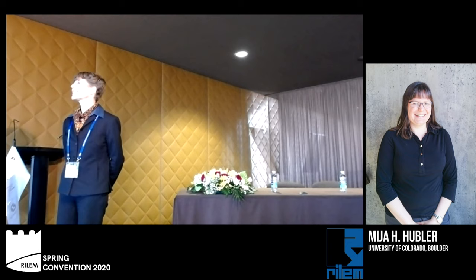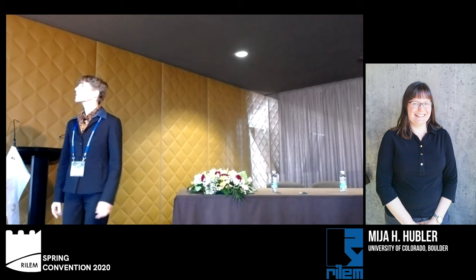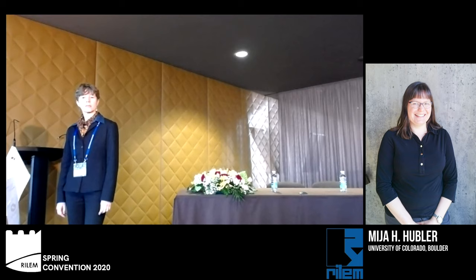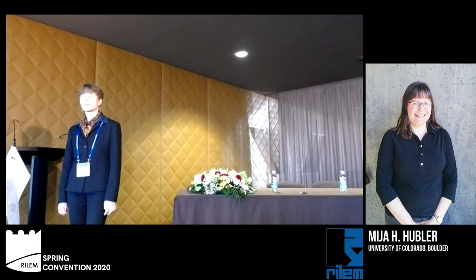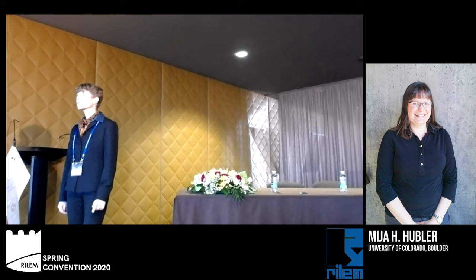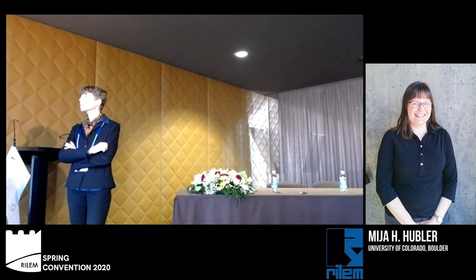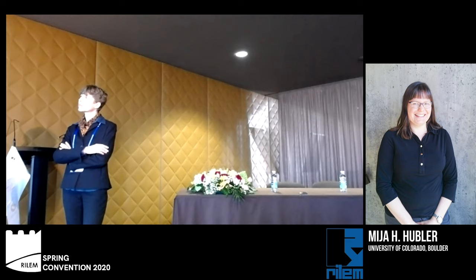So I am aware of studies of creep and crack healing. And so that is the closing of cracks due to the application of load. I think if we could develop the mechanical models for creep, this would naturally enable us to incorporate these kinds of effects, because just as much as there's a configuration distribution for material, there's also a crack distribution in our material. And so if we included this crack distribution in our mechanics, as we did in that same problem, then this would be taken care of.